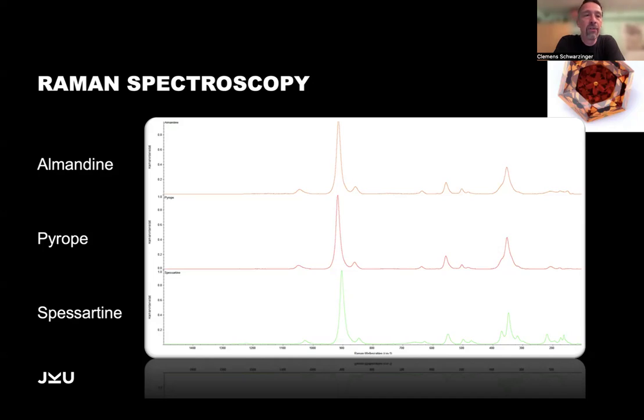And here we have Raman spectroscopy and the spectra of almandine, pyrope, and spessartine. And you see they look pretty much the same at first glance. If you look closely, then you see, okay, this huge peak here shifts a little bit, especially for the spessartine. If you look here at this position, there are 3 peaks overlapping here, here as well. Here you see they start to be separated. So there is a difference between these garnets, and these are pure end members. We're not speaking about mixtures yet.